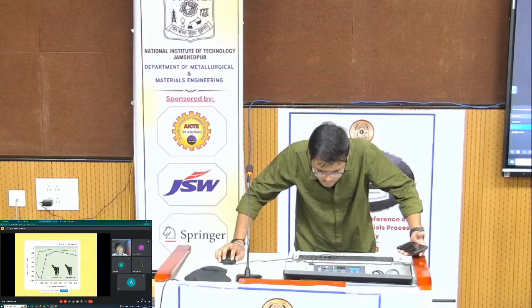So you see here once again the base condition, let us say with carburizing or some other treatment, the green one will give you the base condition. If I do shot peening over that, then I have increased the compressive residual stress further. And that's what is being shown here. So there is a compression here compensated by the inside tension. This is very important. Over the entire volume, the sum of all such layered stresses is 0. So therefore, we want a compressive residual stress.